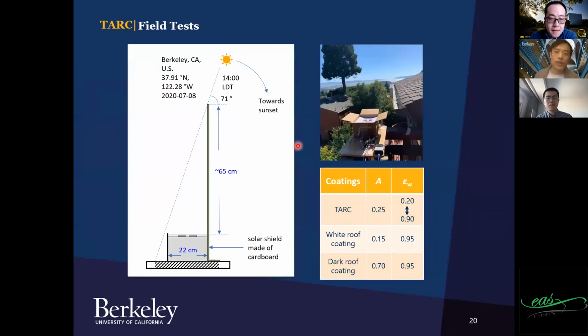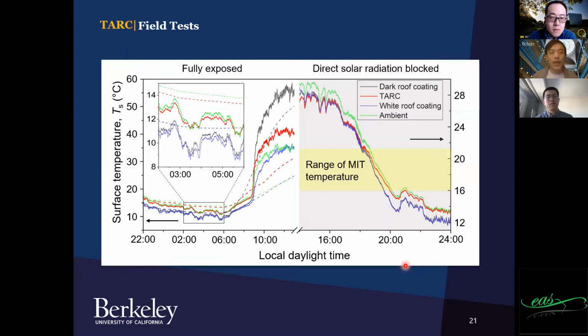And we also conducted a few tests of TARC in Berkeley on a normal roof. We also erected a shield to block the sunlight after 2 p.m. so that we can emulate the case when the sun is blocked by a piece of cloud. And we measured a total of 3 different materials: a TARC, a commercial cool roof coating, and a commercial normal coating we see everywhere. So the cool roof coating has small solar absorptance and a large thermal emittance, while the normal roof coating has a high solar absorptance and high thermal emittance simultaneously. And here are the test results.